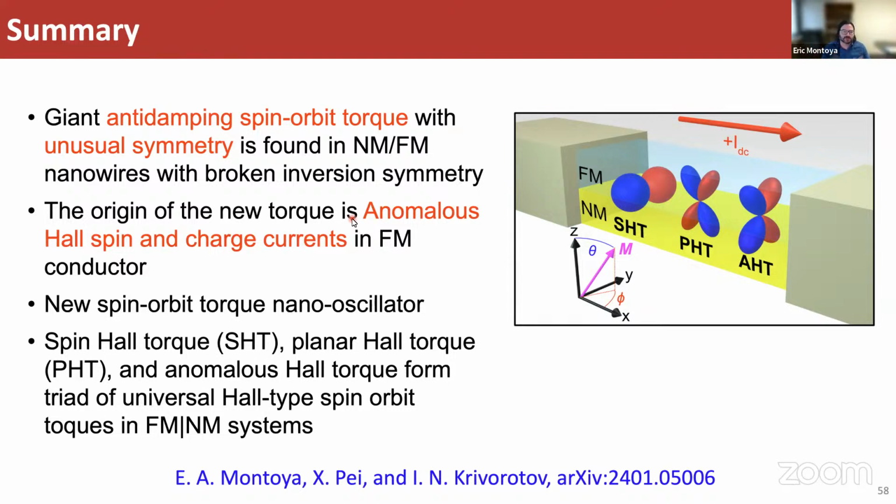I could think of two mechanisms, for example, some magnetic mechanism where you have some third intermediary that you talk to, some magnetic cloud. Or, if you think of it in an sd-like picture, which is the preferred picture I like to think about, these anomalous Hall and planar Hall effects give you a tuning of the s-like electrons, which can then couple to the d-like electrons, and if they have different scattering rates, they can exert torques. But it's just conservation of angular momentum. If you lose angular momentum along magnetization, how can you have a torque?